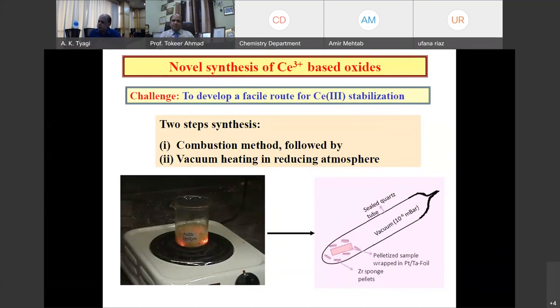Cerium prefers to have 4f0 configuration, 4+. Cerium is difficult to synthesize in 3+ state because Ce3+ is 4f1, Ce4+ is 4f0. And we know 4f1 is much less stable than 4f0. Completely unoccupied, vacant. By combustion, you will never get compounds of cerium in 3+. But what we did, a very innovative thing, this young student of mine, Rakesh, did all this chemistry, his PhD work, incidentally.